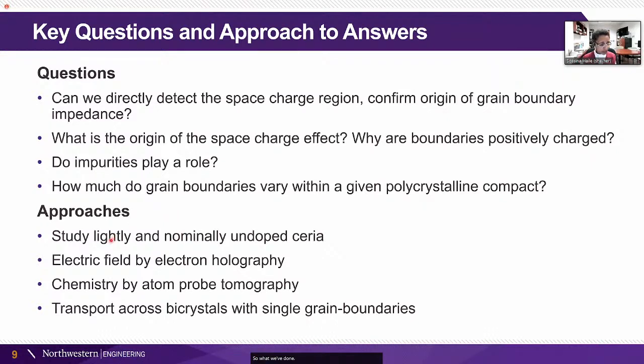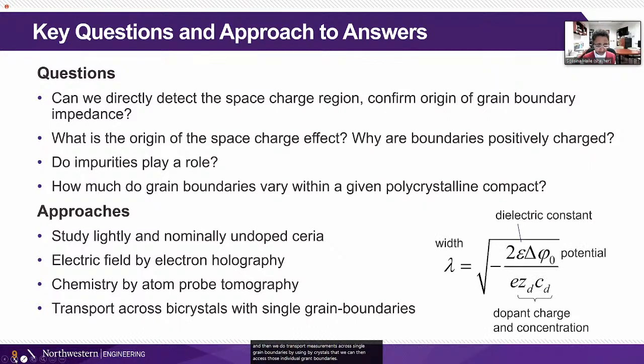So what I'll describe to you is a study of lightly doped and nominally undoped ceria. We have probed the interfacial charge by using electron holography. We studied the chemistry by using atom probe tomography. And then we do transport measurements across single grain boundaries by using bicrystals, so that we can access those individual grain boundaries. One thing I'll say is that the reason we've used lightly doped ceria is because the width of the space charge region is inversely proportional to the square root of the dopant concentration. And so the smaller the dopant concentration, the larger the width of the space charge region, if it really is a space charge, and therefore it makes it easier for us to detect it.